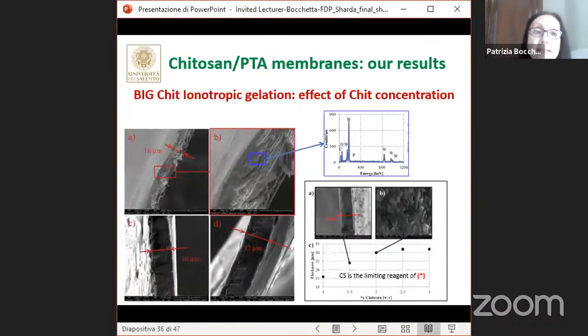This is confirmed by the experiments carried out at constant concentration of acid and variable concentration of chitosan. We have calculated the stoichiometric quantity of acid necessary to cross-link all the amine groups of chitosan, and the concentration is 0.034 mol per liter, a value strongly lower than the one we have used in this experiment, which is 0.76 molar. So this indicates that chitosan is the limiting reagent of the ionotropic gelation reaction.